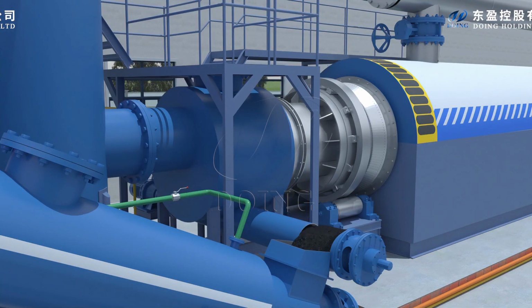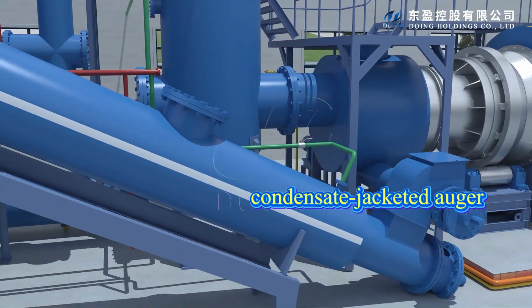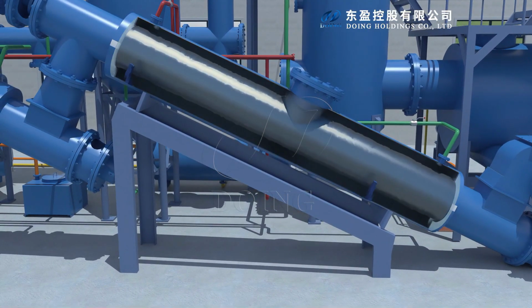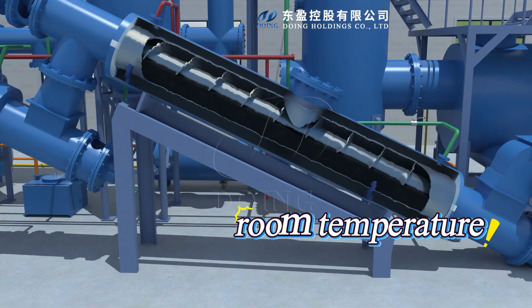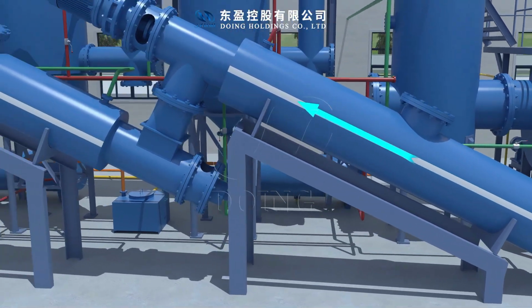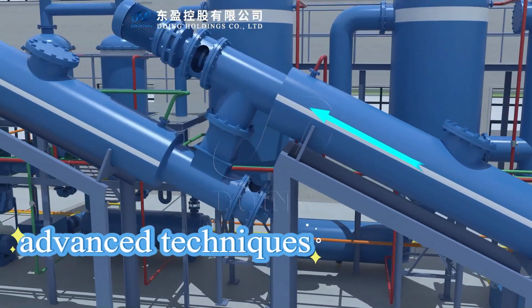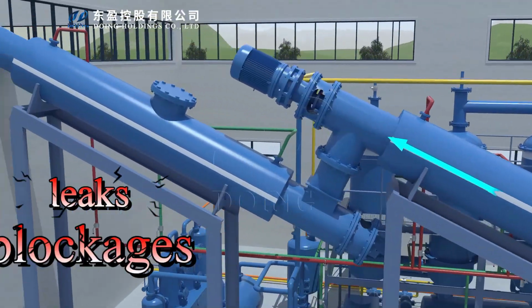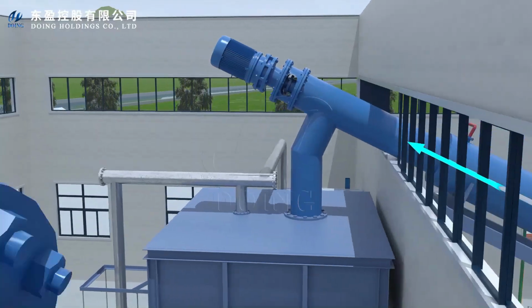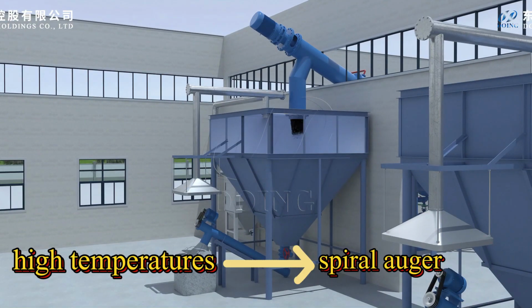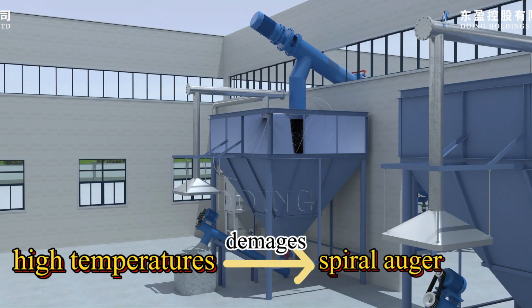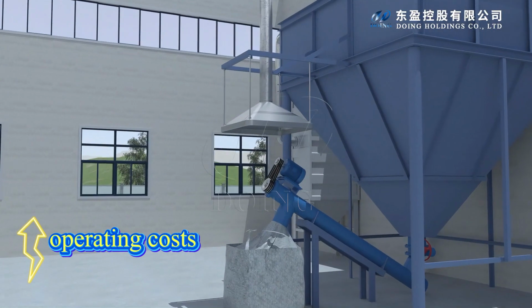The second method uses a condensate jacket auger for cooling, so that the carbon black is discharged at a temperature close to room temperature. However, the latter requires advanced techniques. Otherwise, leaks or blockages may occur. Furthermore, the auger can easily become damaged by high temperatures, increasing the equipment's operating costs.